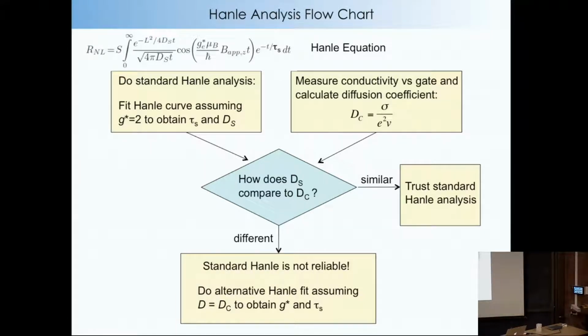If they're similar, it depends what you consider similar, you say, let's trust the standard method, and the width is going to tell you the spin lifetimes and so forth. But if they're different, in our case they were different by about a factor of 8, which is just not physical. And in their work, they're off by a factor of maybe 20 or more, I forget. If they're different, then the standard Hanle is not reliable.